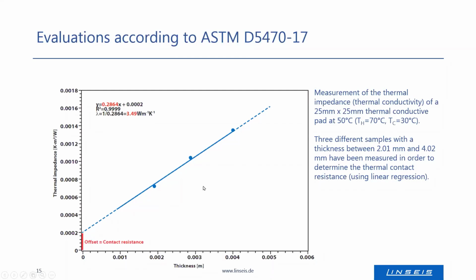In this example you can see the measurement of a thermoconductive pad. The sample temperature was 50 degrees. The hot plate had a temperature of 70 degrees and the cold one 30 degrees. And one obtained a thermal conductivity of roughly 3.5 watts per meter Kelvin.